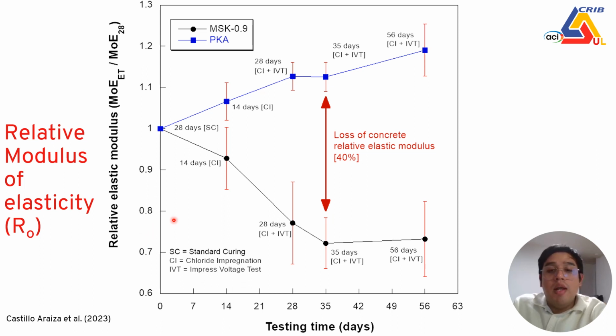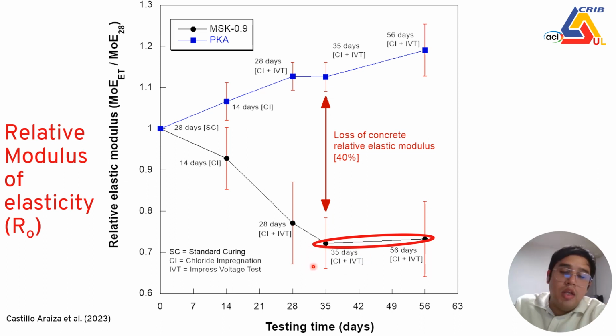So what I can say is that here we observe something really important: after 35 days of electromigration treatment, we don't really see an increase in the loss of performance of the concrete. So we think that with this percentage, we can really distinguish between a reactive aggregate and a non-reactive aggregate.